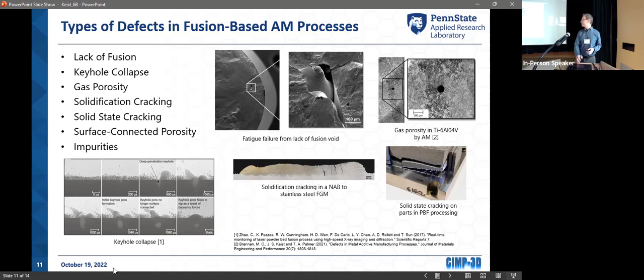And then finally, additive manufacturing can build a lot of stresses, and that can cause solid state cracking. And this is an extreme example here where we had a build plate actually crack directly off the plate just by building this. And that's another area that we're very concerned about. There's other things like surface connected porosity that has to do with the additive manufacturing process. You can get around that by just machining your surfaces as needed. And finally, impurities can find their way in as well.